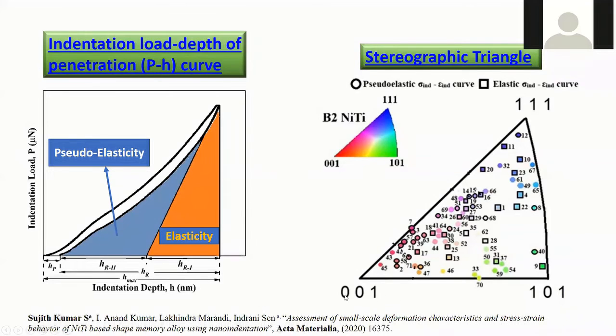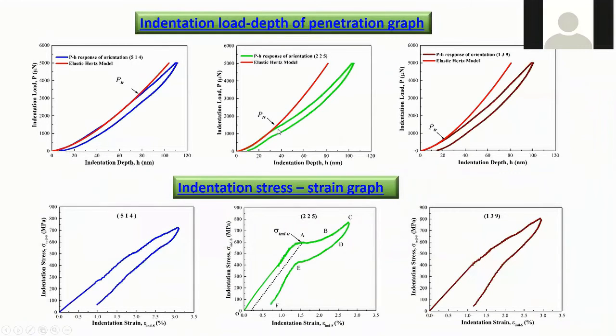So we have done this kind of indentation study on several grains, and you can see that we almost have covered the entire stereographic triangle having different orientations. The colors here signify the colors as per the stereographic triangle of the electron backscattered diffraction image. And what we could figure out is that the P-h curves for these grains are completely different. And we have a unique way of converting this to a stress strain diagram. And we have seen that again, the stress strain curves and the P-h curves for these are completely different.